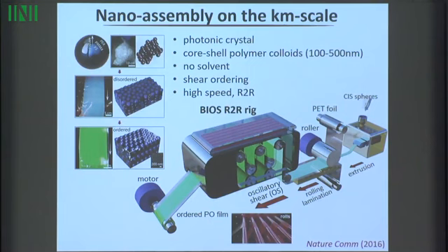They're very small because it's only when you make them small enough, on the scale of the wavelength of light, that you start to get these really interesting color effects. Only when I stack them and they're a particular size will I, say, get a green out of the system. So we make films of this, and then what we find is that when we shear this film, so the solvent is entirely just this shell here, we shear them against each other, they order perfectly.